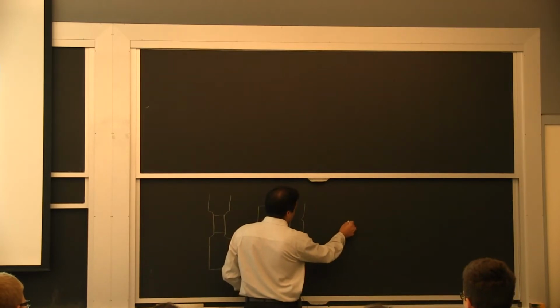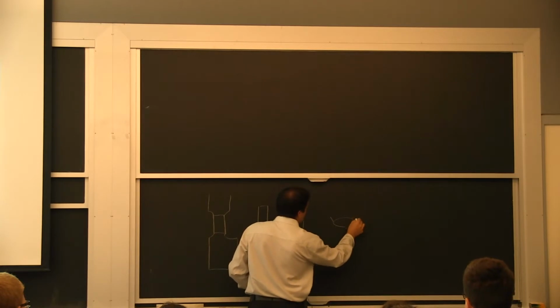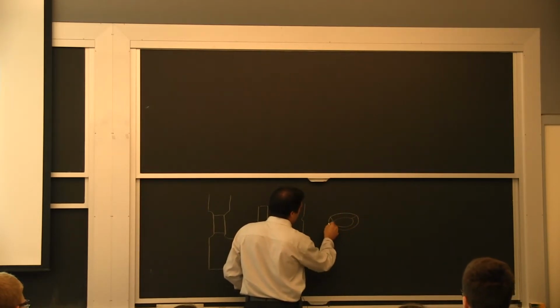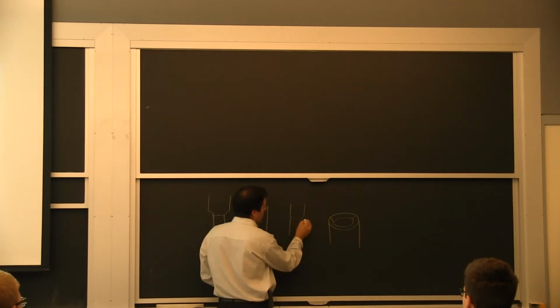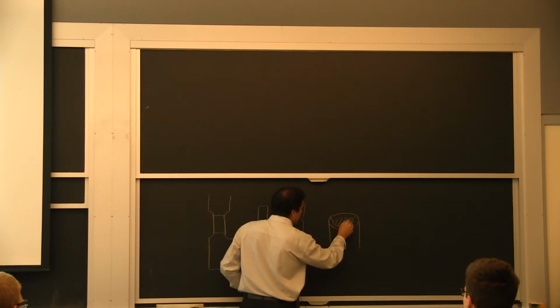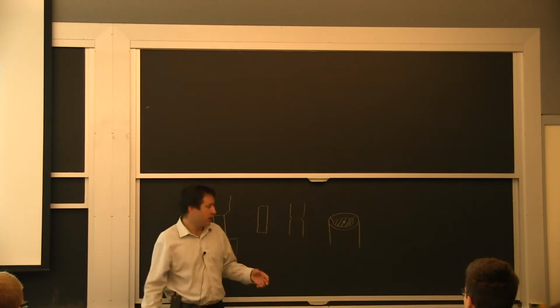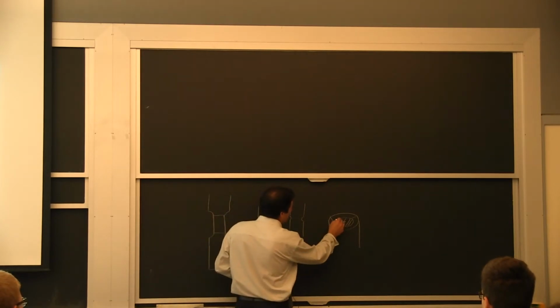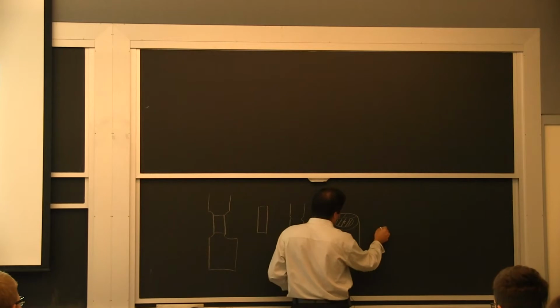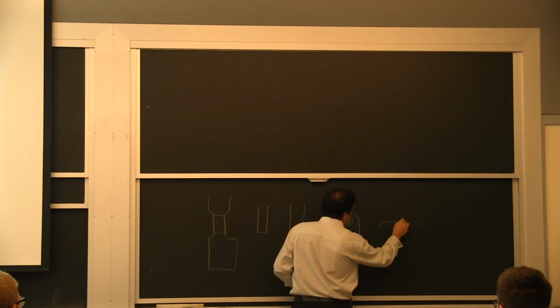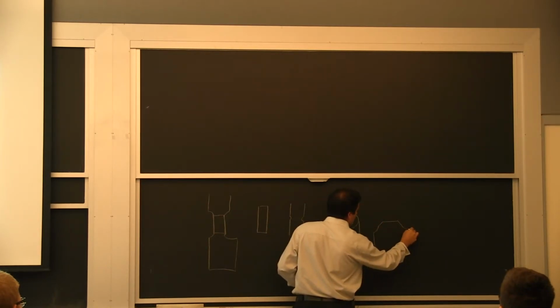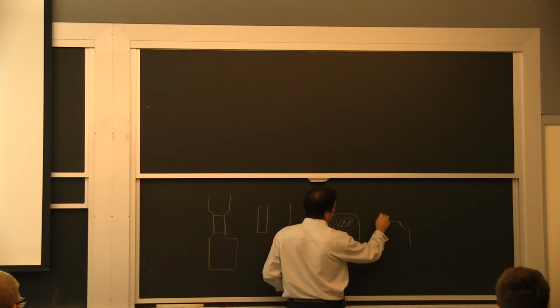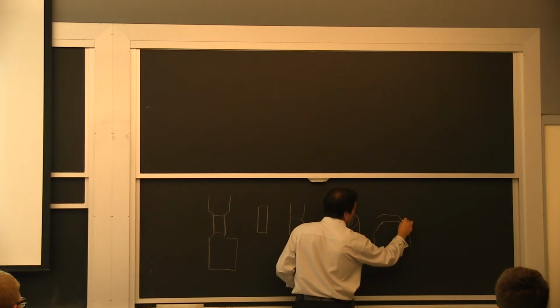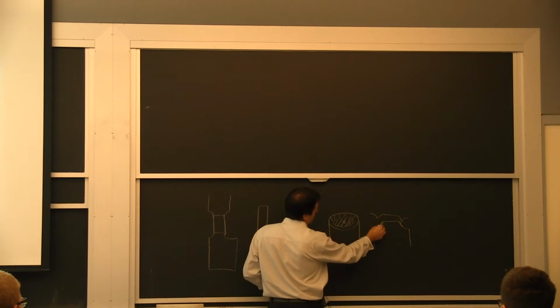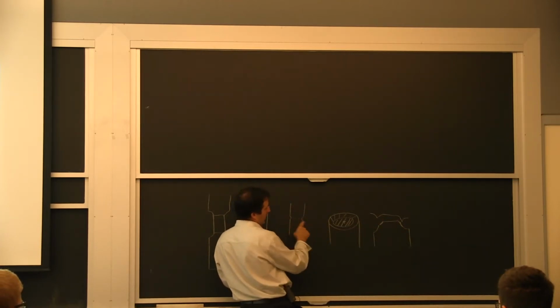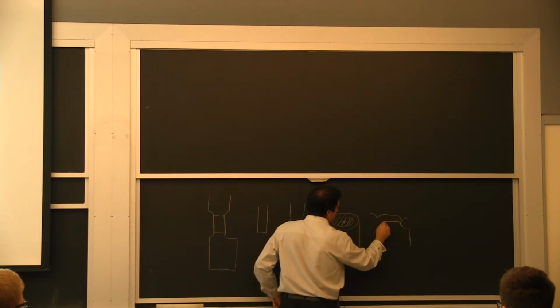propagates. And the way the crack will propagate, if I look a little bit more at an angle here at this sample, it will look like what we call a cone and cup. So you'll have this essentially going perpendicular here. So this is where it started. It will normally snap somewhere in the middle because you get more tension there with the stress concentration as you're forming the neck. And then when you get close to the edge, this will tend to be at 45 degrees. So if I do a side view, it will look like this. One side is going to be like this, and then you have your neck. So this is the shear fracture here, and the matching face will be like this. So this used to connect to here, and that was our neck. And now what we've introduced is a transverse crack and then these shear lips.